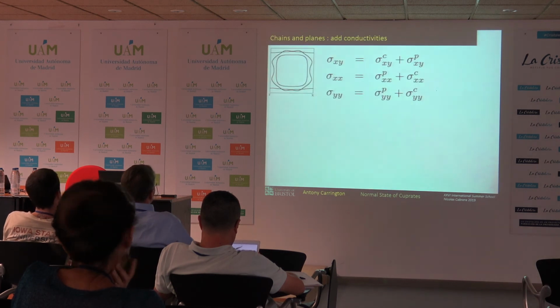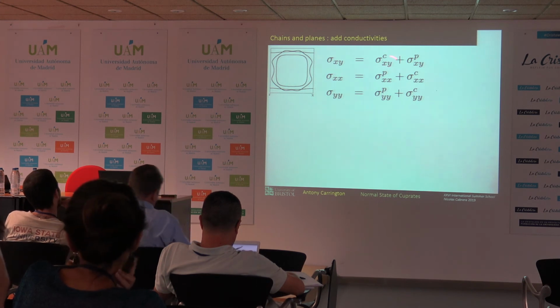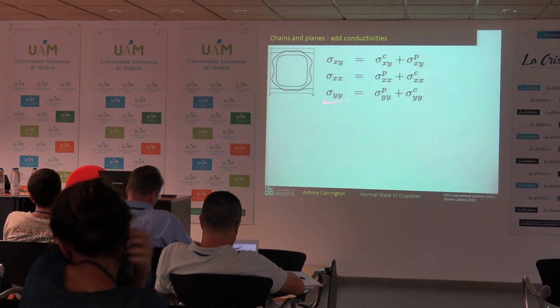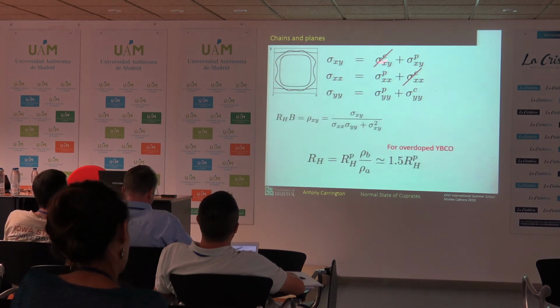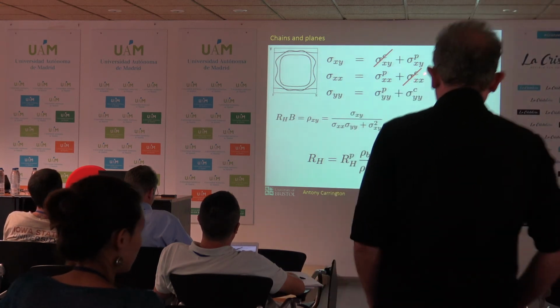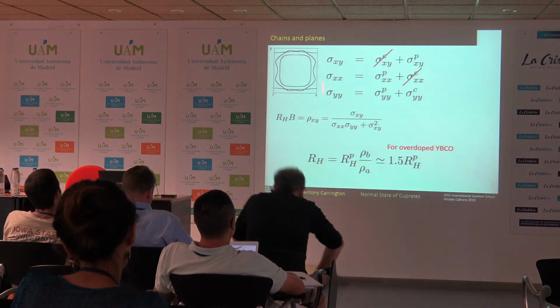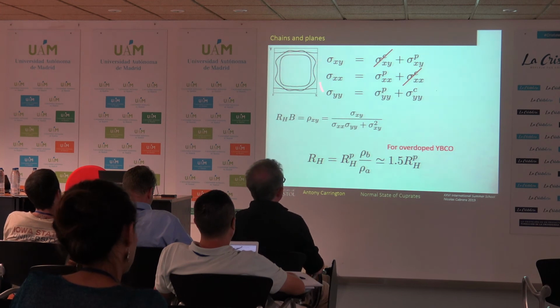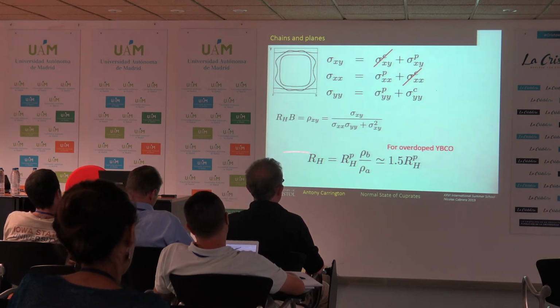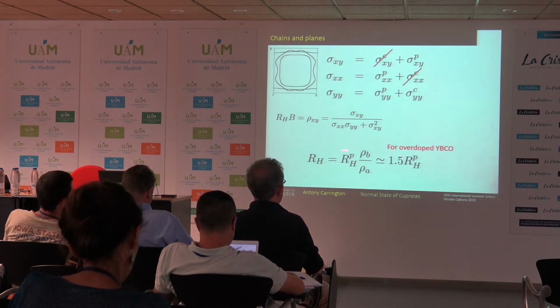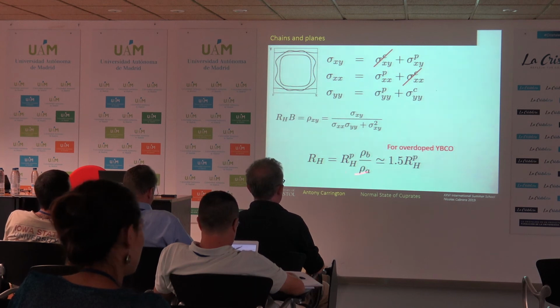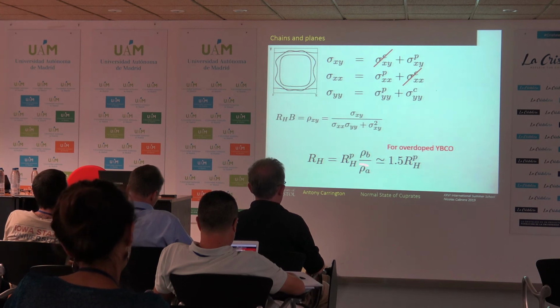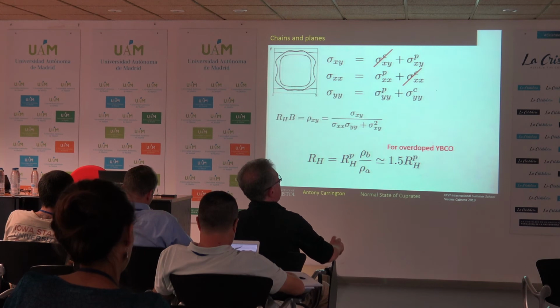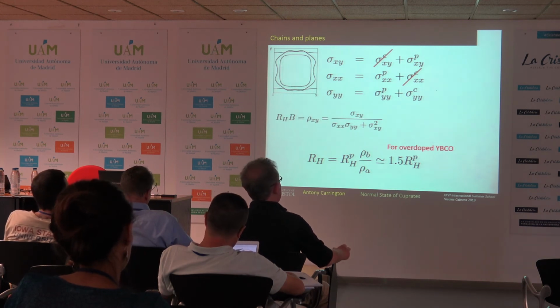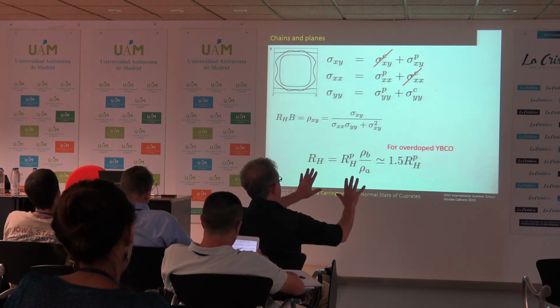So therefore, if we look at YBCO, then we would expect there to be a response to the chains and a strong response to the planes, and we should add the conductivities together. But we know that this one should be 0, and in the x direction, there's no contribution from the chains. So this is the x direction, so we get a contribution in that direction because this quasi-one-dimensional Fermi surface gives rise to currents moving that way, but not that way. So you cross these two out, and then with a small bit of mathematics, you can show that the Hall coefficient that you measure is essentially related to the one that you would get if you didn't have the chains, multiplied by the ratio of the resistivity along B divided by the resistivity along A. And you can kind of understand this. Basically what it's saying is that if you put the current along the x direction, some of the current's been taken up by the chains, but it hasn't got a Hall response. Okay.